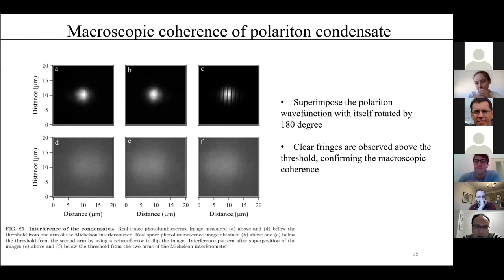Firstly, this one is from a reflector. I think we got the interference fringes from the first one, the one you mentioned in your first question. Secondly, the laser spot is very large, because we found that if we use the pulsed laser, the spot size is small, it can really burn and destroy the perovskite.